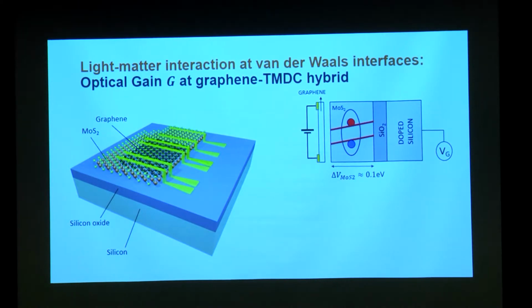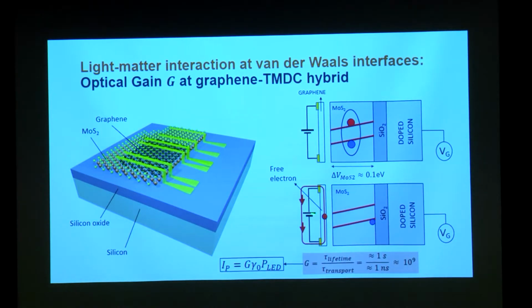See, the idea is when you shine light on the molybdenum disulfide, an exciton forms. The hole is in the valence band and the electron is in the conduction band. The moment they form, the electron essentially jumps out and goes into the graphene layer and conducts electricity. It goes on conducting for a very long time, because graphene and molybdenum disulfide are physically separated. The electron cannot jump back, and hence the lifetime of these structures is extremely long, about 1 second. The transport time along the graphene is very small, so that gives you a huge optical gain. So that's what gives electricity.